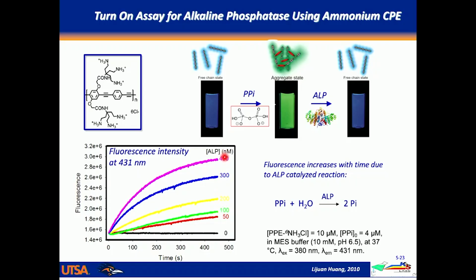It turns out, for those of you who might know something about phosphatase enzymes like ALP, they always require the presence of a divalent metal like zinc or magnesium in the solution, and that can interfere with the copper that's added to that other enzyme system. So this system that's metal-free essentially frees us from that limitation, and it's much more generalizable.